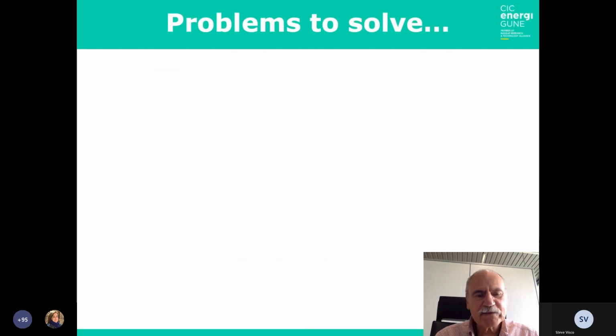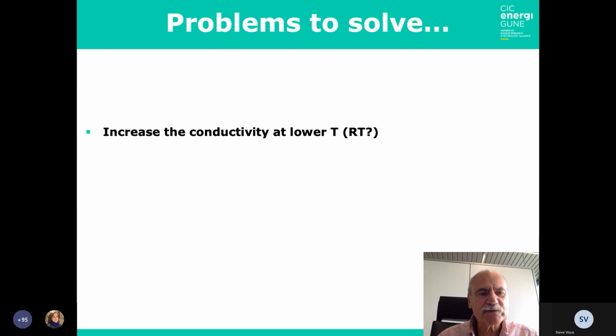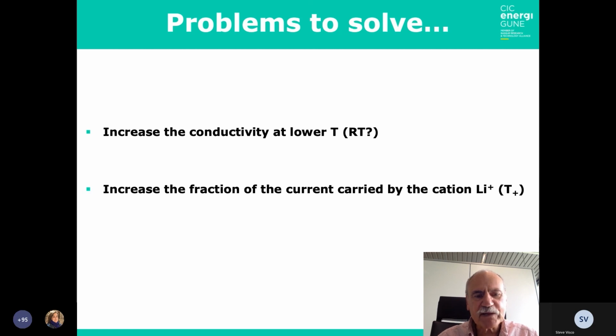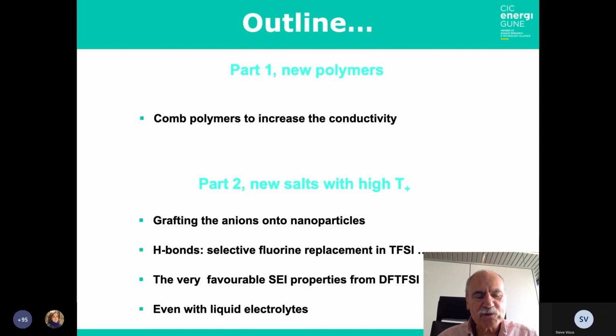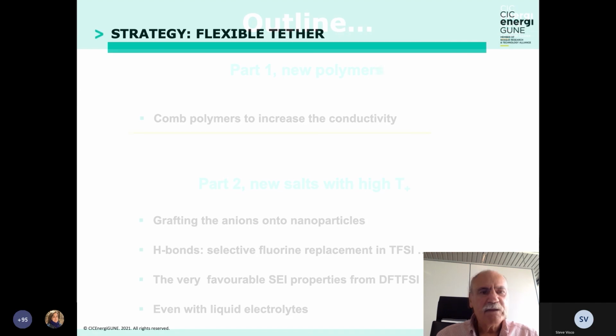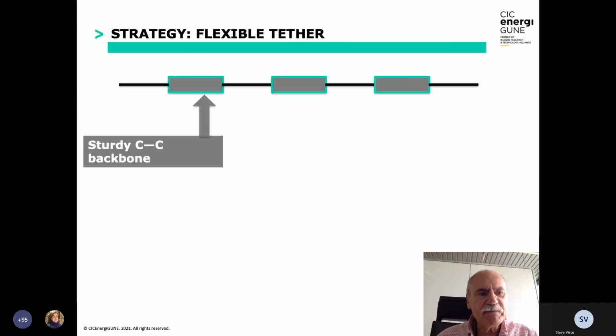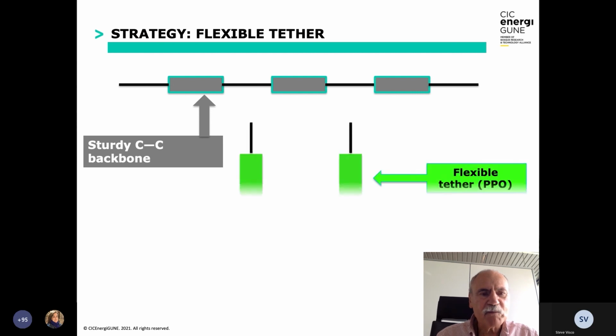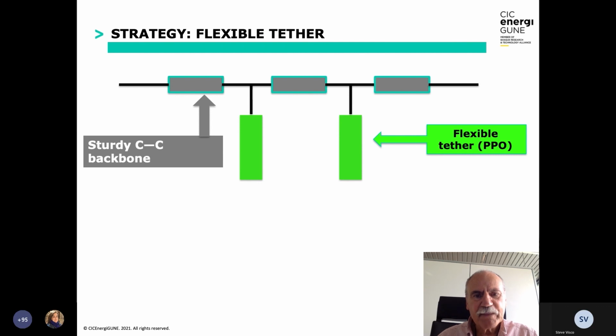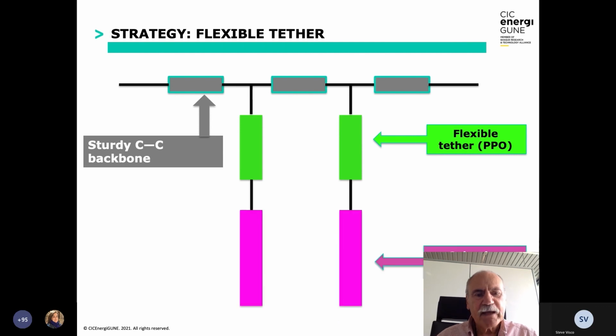If you want to improve on this situation, try to decrease the operating temperature. You need to increase the conductivity at lower temperature. You need to increase the fraction of the current which is carried by the cation lithium, what I call T plus transport number, and you need to keep the processability. For this, we thought of using copolymers to increase the conductivity, and the idea is to take a sturdy C-C backbone polymer that would be resistant mechanically to oxidation and reduction that are going to be present in the battery operation, to which you attach a flexible tether, which is in this case PPO, polypropylene oxide,